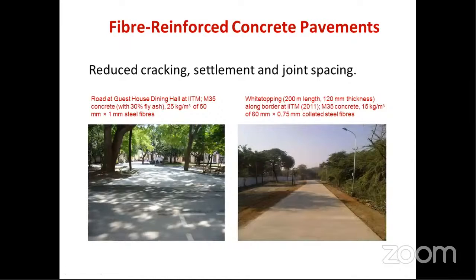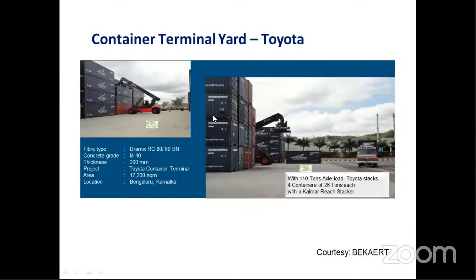And not only worldwide, we can find some examples in our place also. In Chennai, at IIT Madras, they have provided a road which is marching towards the dining hall. This entire pavement is made up of SFRC with the incorporation of steel fibers, and 30% fly ash has been added. 25 kg per meter cube, that is around 0.25% volume fraction of steel fibers, has been added, and this is a concrete topping made with SFRC, steel fiber reinforced concrete, available at IIT Madras. The grade of concrete is M35. It can be adopted for any type of grading. And the purpose is that it is going to reduce the settlement, right? Those problems can be avoided.